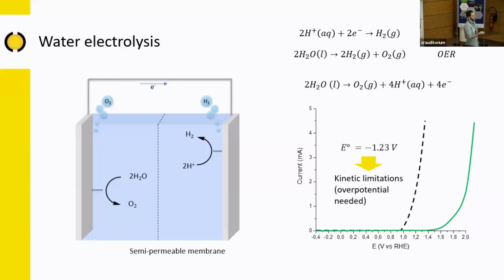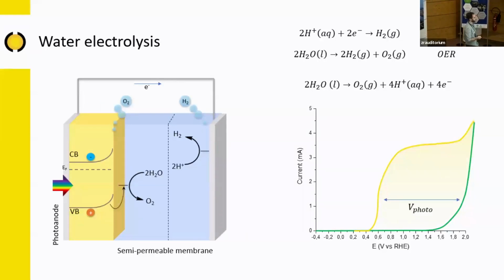So typically, if we have kinetics limitation for the charge transfer process, which we always have, we get a much larger potential. So this becomes not really competitive with other technologies to produce hydrogen. Now, one solution to this issue is to replace one of the electrodes. Both of the electrodes can have different configurations, but in the simplest one, we replace the anode with a photoanode, in particular a semiconductor photoanode that is able to absorb some light. Typically, this is visible light provided by sunlight. So it absorbs this light, excites an electron-hole pair, and uses the built-in photopotential to shift this potential to much lower values. So basically, we need much less energy, much less external bias to promote the same reaction.